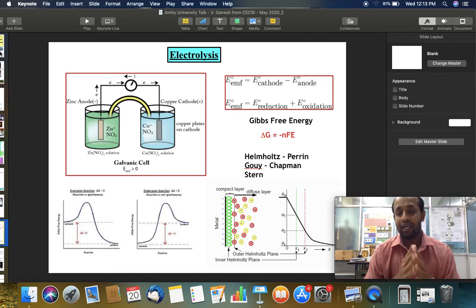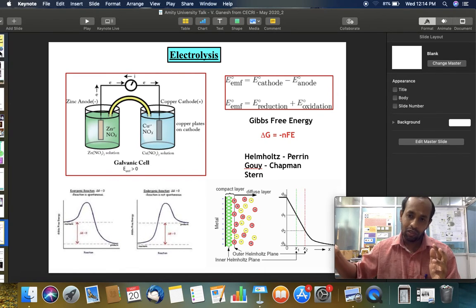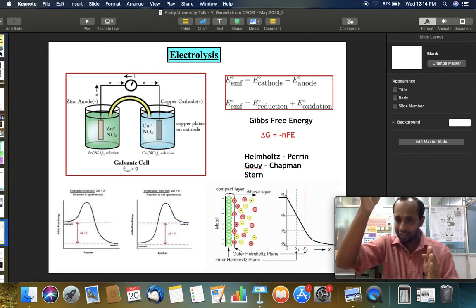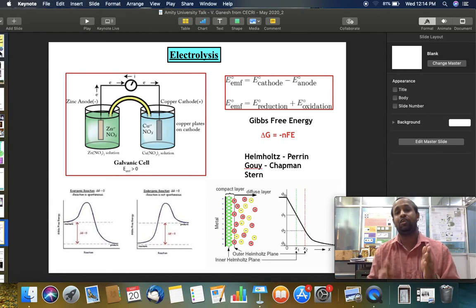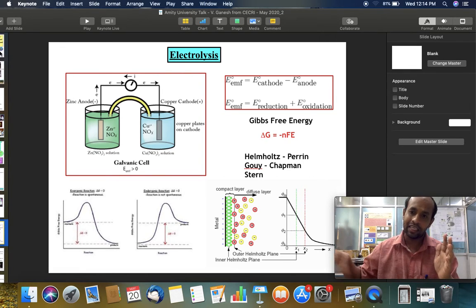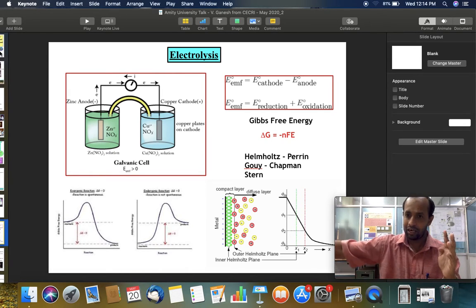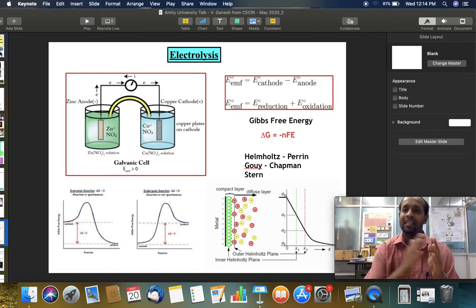But if you measure experimentally, the capacitance theoretically predicted from the Helmholtz-Perrin model does not match the experimentally measured capacitance value, because we do know that in a liquid the molecules or species are in random motion, and you cannot have a fixed layer of charges in the electrolyte part. So, in order to rectify that model, the next model was proposed by Gouy and Chapman, where they proposed that the molecules in the electrolyte part are in random motion. They are diffused into the electrolyte part, and that gives you capacitance.